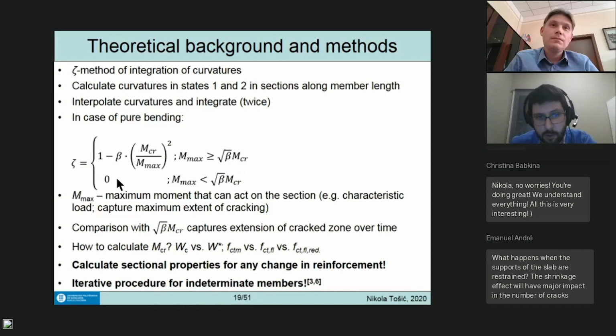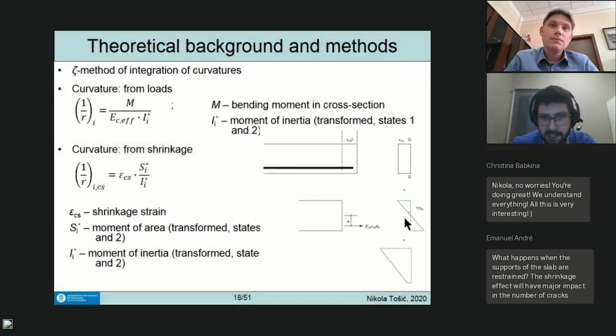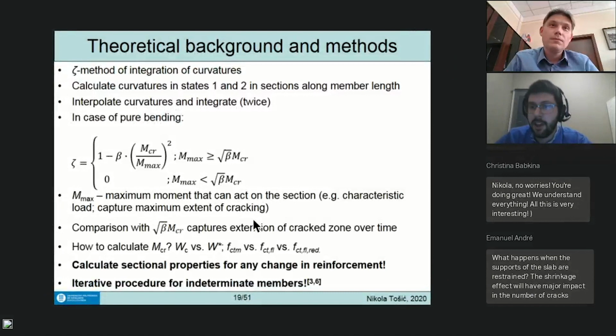When beta is 0.5 for the long-term deflection, square root of 0.5 is around 0.67. So that amounts to pretty much saying that over time you lose about a third of your cracking moment due to shrinkage. And for a variety of cross sections, you can calculate this yourself: you can calculate relatively simply how much tension you are producing by shrinkage, and you will see how much you are reducing your flexural tensile strength.